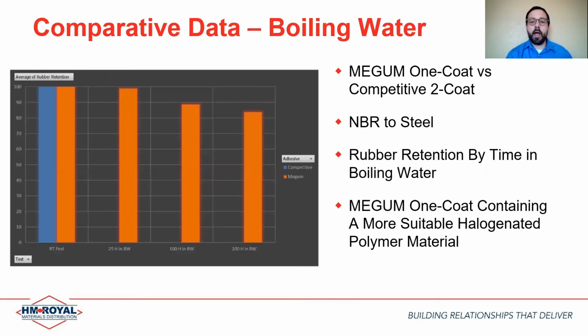A similar test, this is not in a dry condition, but in a wet environment. So what we've done here is we've taken a Megum OneCoat versus a competitive two-coat system. These are both nitrile to steel, and these results are still showing rubber retention by time, but this is in a boiling water test, which is an excellent test for showing long-term performance of adhesive systems. In this specific test, we see that while Megum does show some loss in performance over time at various temperatures, the results compared to the competitive primer are better.